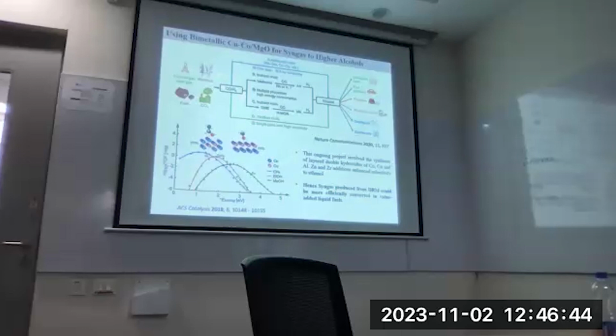So this is pretty easy because rather than using CO2, if I use just this mixture of syngas, like carbon monoxide and hydrogen, I can get ethanol very easily. From the most recent catalyst I was working on, I was getting almost 80% conversion of this mixture, a very stable catalyst. I'm just using copper, cobalt, and aluminum, and I can make the catalyst overnight, at large scales. So this is the more viable method of doing CO2 utilization.